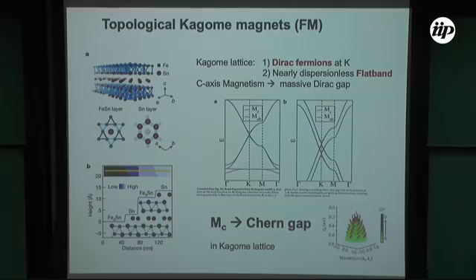Even just by the lattice connectivity, the lattice network, you have both Dirac fermions and a flat band, right? Now, if you have magnetism, especially out-of-plane magnetism or some component of out-of-plane magnetism, those Dirac fermions will have time reversal symmetry broken. You'll open a gap. So in other words, you'll have a natural topological magnet realized in a Kagome magnet.